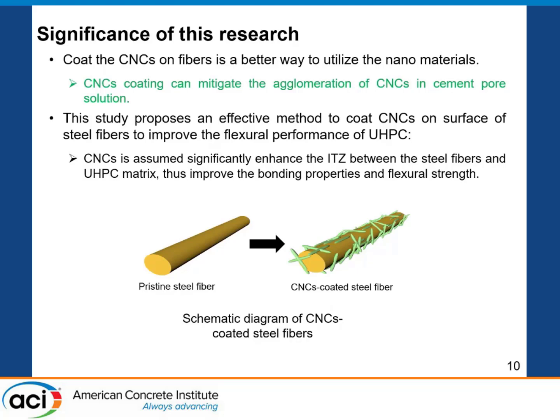So we think that if we coat the CNC materials on the steel fibers, it is a better way to utilize such nanomaterials. In that way, we can mitigate the agglomerations of the CNCs in a cement pore solution. So in this study, we proposed a way to coat the CNCs on the surface of steel fibers to improve the flexural properties.